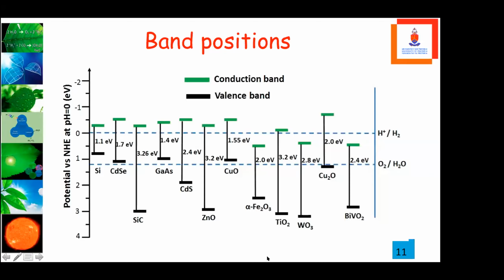Okay, thanks. Bismuth has not been used here, but with the dope, when vanadium oxide is doped with bismuth, that's when people have reported something there. But because of its position very far from hydrogen evolution band gap, and also very far from oxygen evolution band gap, it is still found to be non-suitable. But we hope your guidance can help us to make bismuth oxide, but we will make it a heterostructure with hematite. I'm just sold out to hematite.